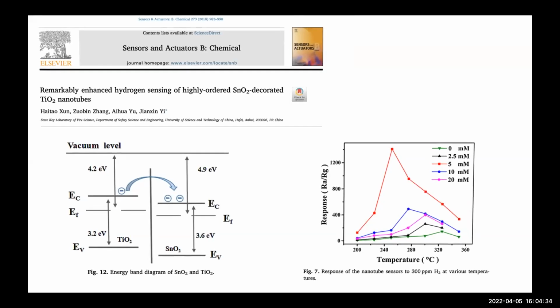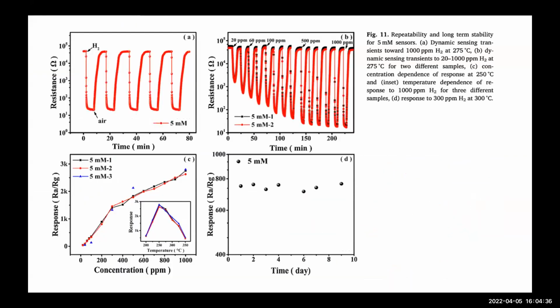Now next we will discuss the 5 continuous cycles for checking the long-term stability of this composite sensor. The response transient in 1000 ppm hydrogen, recovery, and then baseline in atmosphere were excellently reproduced. So you can see from all these graphs that the result demonstrated clearly excellent reproducibility and long-term stability for the 5 mM sensor.